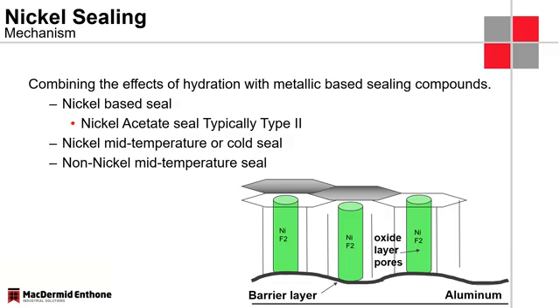The nickel acetate is a little bit of a combination of both these sealing mechanisms. It precipitates nickel into the pores, but at the same time, at around 80 degrees, we'll have a rehydration of the oxide layer as well, and that will further help closing up these pores, making that structure more compact and give very good corrosion resistance.